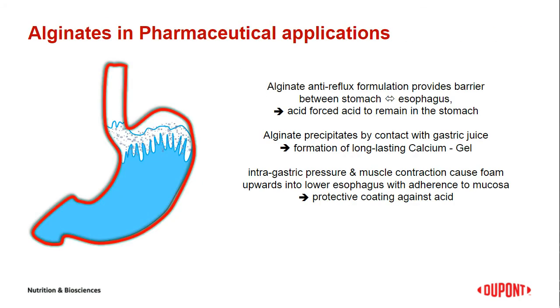One of the applications of high importance in pharmaceutical use is anti-reflux formulations, where the alginate is used as the API. When a formulation containing alginates reaches the stomach, the polymer interacts with the gastric juices and forms strong gels which remain in the stomach for up to 3 hours. Calcium and/or sodium bicarbonate salts in the formulation form carbon dioxide in the acid environment of the stomach, which is entrapped in the gel and makes the gel buoyant.